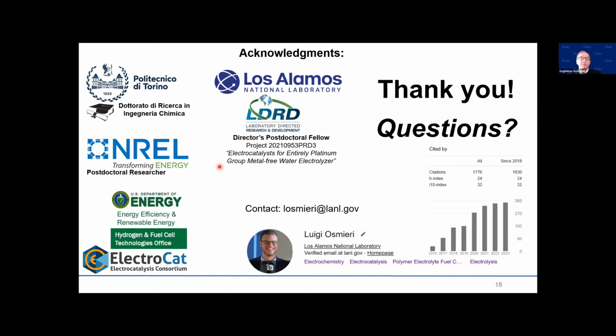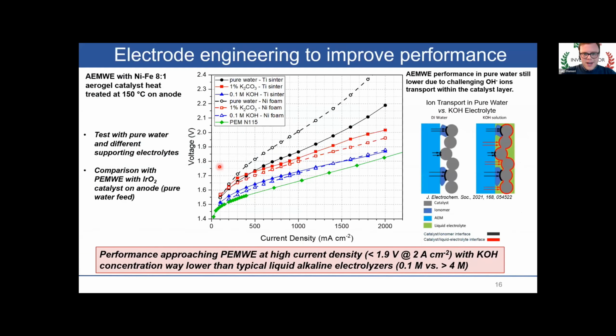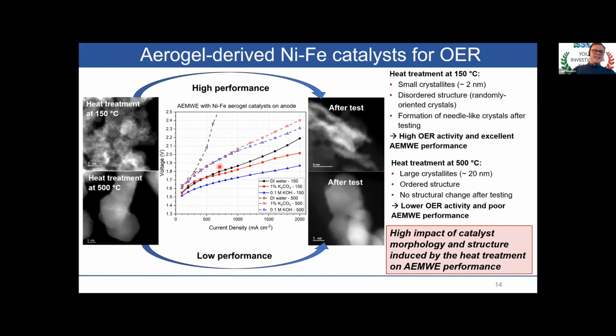Thank you. Natalie? Yes, possibly a specific question. Why in the aerogels do the lower temperature yield gels perform better than the higher temperature yield ones? Yes, so what we have basically found is that when we heat treated at this low temperature, the modification compared to the original aerogel without any heat treatment is basically minimal. At this low temperature, we basically just desorb some moisture that was absorbed on the original aerogel. We did not really modify the structure. While heat treating at very high temperature, we create these rock salt crystals, which have the structure of a nickel oxide.